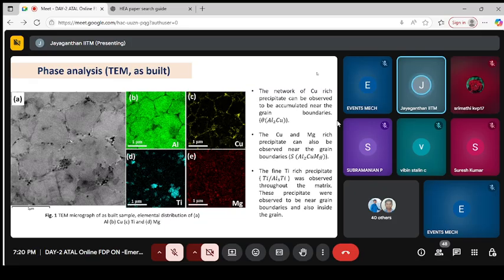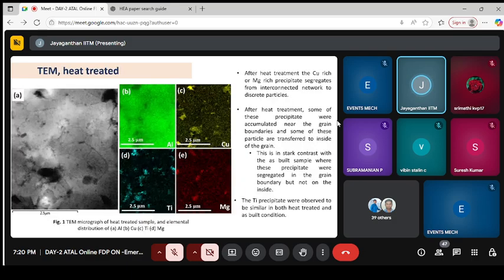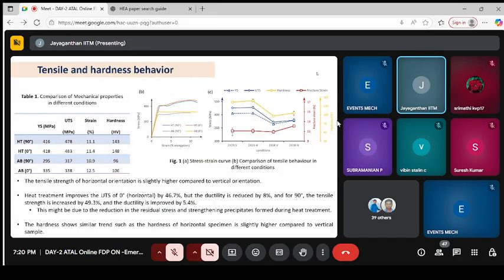Again, having mentioned that it tends to form theta precipitate and S precipitate, their typical precipitate size is almost submicron. That's what we want to highlight by doing TEM. We did it for the as-built sample as well as for the heat treated sample. Their size and shape tend to change. We characterize the precipitate being formed through SEM and TEM to look at morphology, how they look. And again, having done complete tensile property and hardness property testing, what I want to conclude, if you look at, you can see extreme left. Hope this slide is visible for all of you.